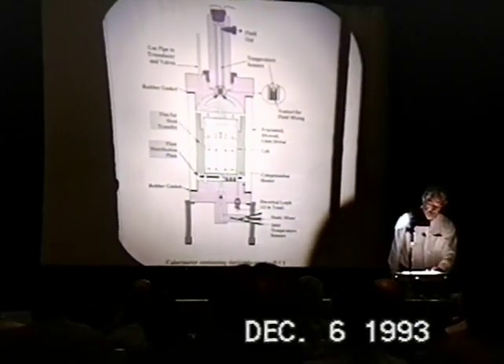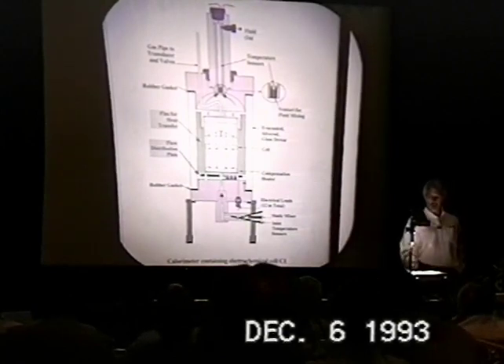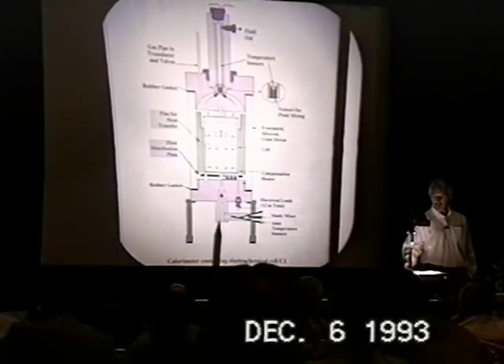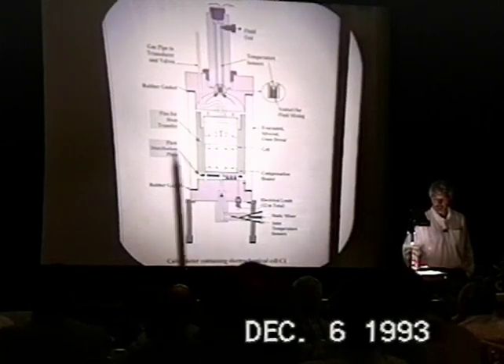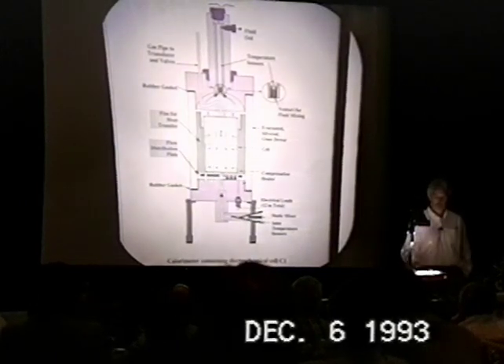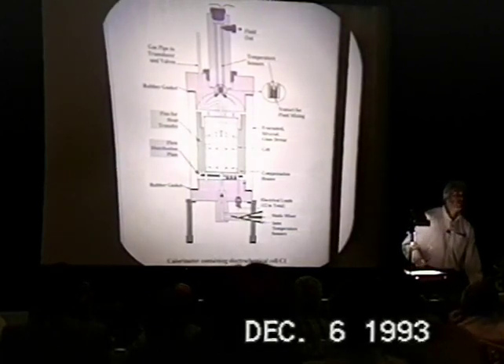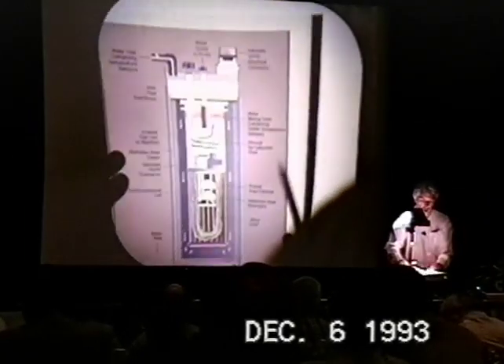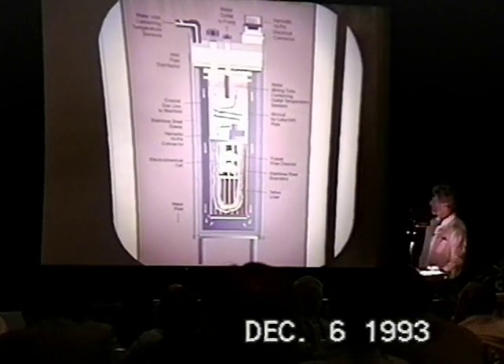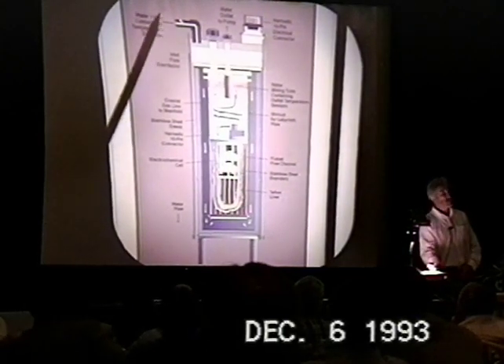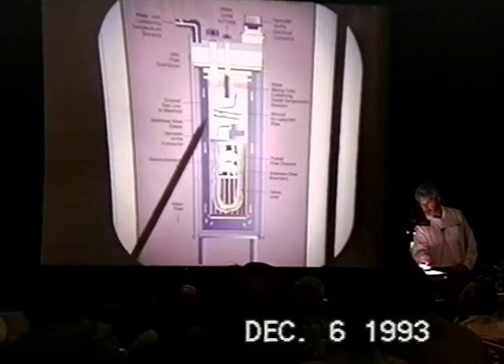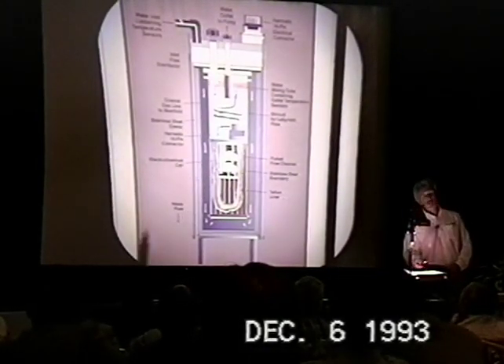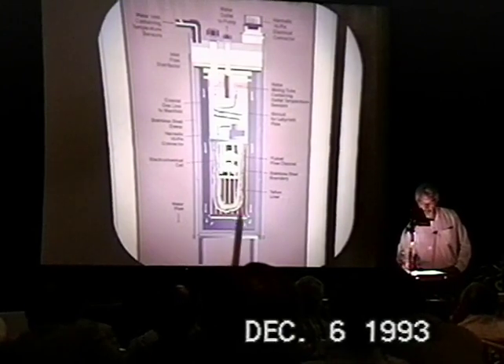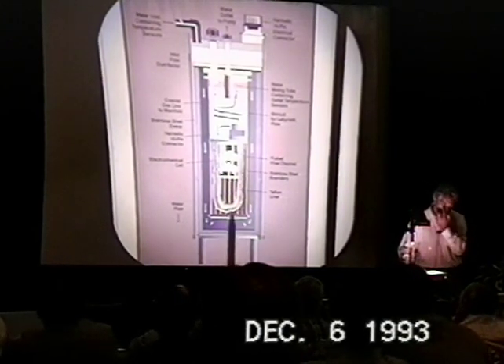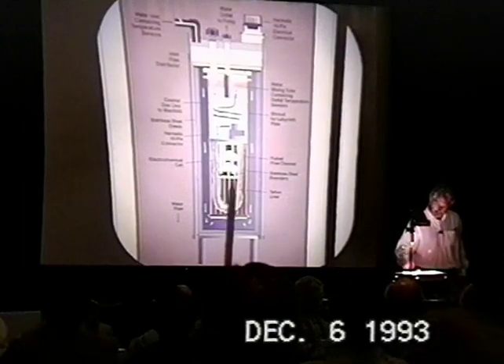Just to orient you, if you remember our old calorimeters, this is the object that's placed in the constant temperature bath, taking fluid from the bath past 2 temperature sensors, past the cell, past 2 temperature sensors, and out to the pumps. We've changed this design by the incorporation of a labyrinth, so the flow, instead of coming in from the bottom and going out the top, comes in from the top and goes out the top. The flow comes in from the bath past the same 2 temperature sensors, goes down this inner wall, in through the labyrinth, round the bottom, past the cell, up through a fluted flow path, picking up the heat from the cell and then back out the top.